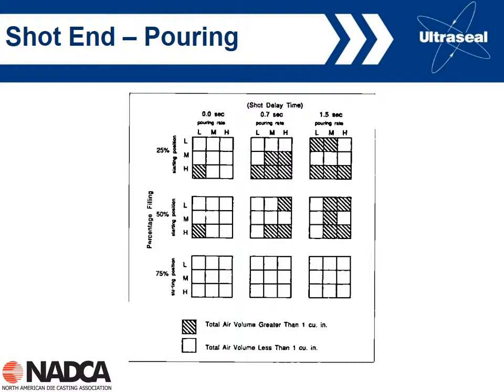What we're showing from the legend is that the shaded areas are high porosity, more than 1 cubic inch of air entrapped. The unshaded areas are where we want to be, with lower amounts of trapped air. What it's showing me is that, at least for the low percentage fills, 25 and 50, as we increase the delay time, we're actually increasing the amount of entrapped air. So it's suggesting that waiting for the turbulence from the pour to go away is actually hurting us instead of helping.